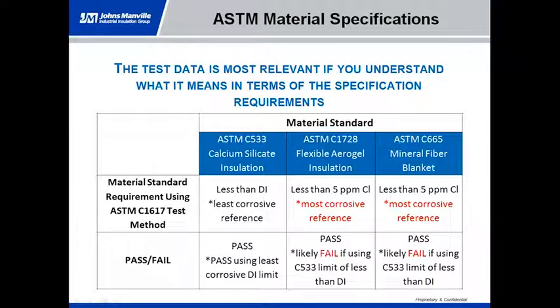Now, if you look at ASTM C1728, which is for flexible aerogel insulation, or ASTM C665, they use a less than 5 parts per million chloride solution. And again, that's the most corrosive reference that there is. You could go as high as 10, but those are extreme cases. Now again, looking at pass-fail, they pass their respective requirements in that they're less than 5 parts per million. But if you're comparing it to the DI water limit, they would fail because they're above the DI water, but they're below the 5 part per million threshold.